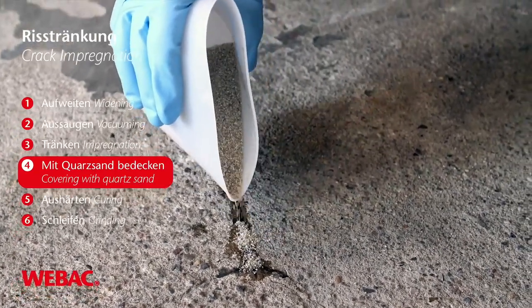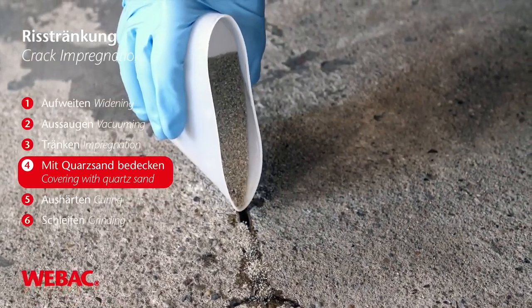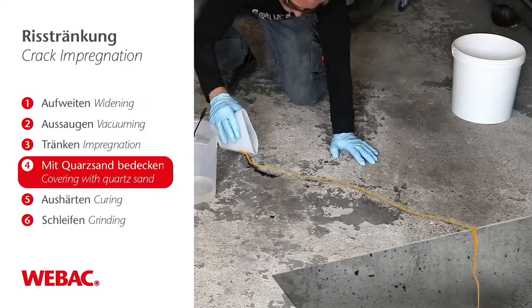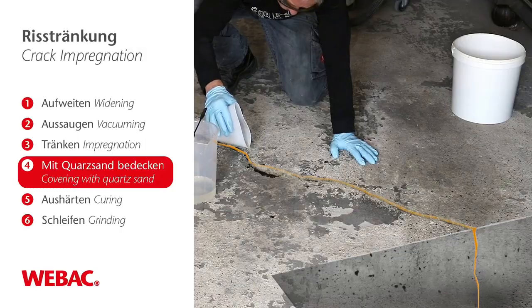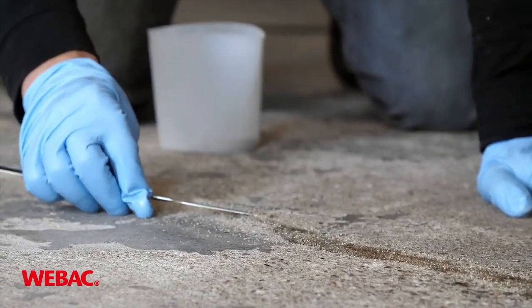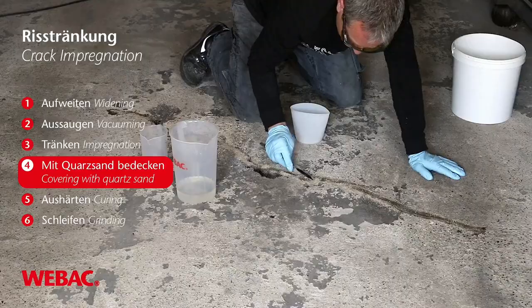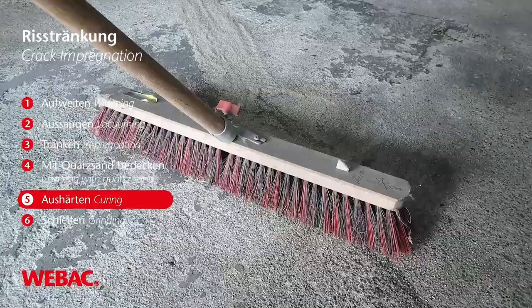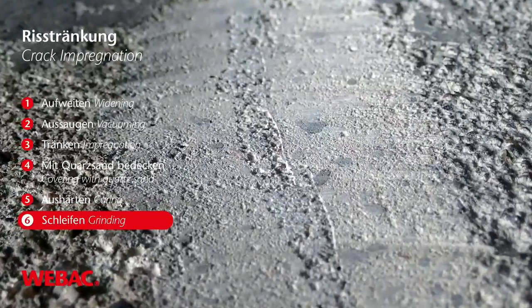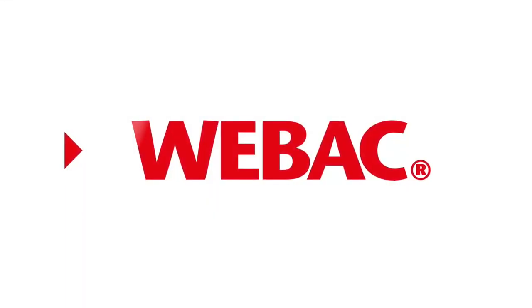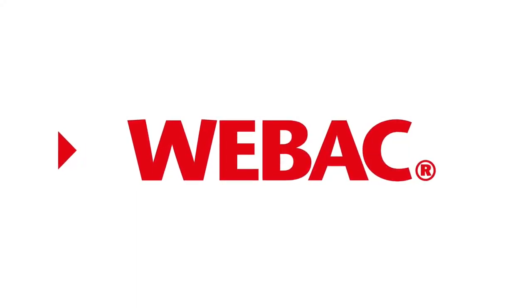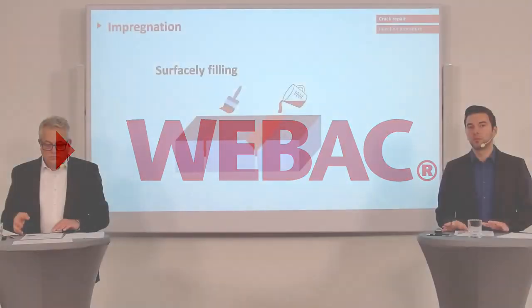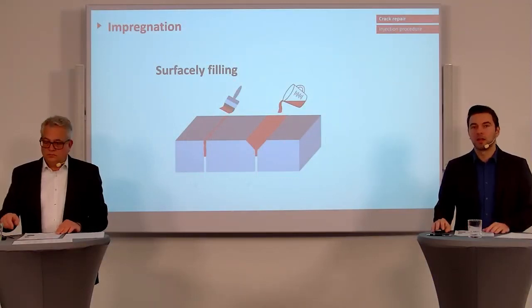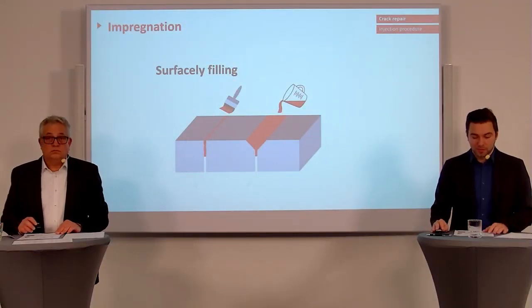Once you achieve the filling grade to the surface, you can just apply some quartz sand to smoothen the surface. And after curing, which is going to follow in a couple of hours, so the material needs some time for reaction, and after it's cured, you just brush off the quartz sand, and afterwards you can grind the surface again to make it smooth, and afterwards you can start to apply, for example, a coating system.